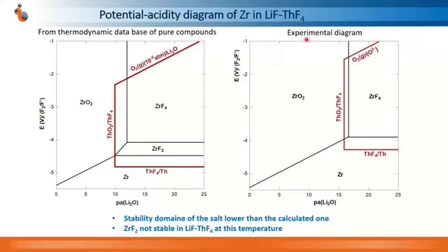Just a comment about lithium fluoride, thorium fluoride salt. We did some experimental studies of zirconium in this molten salt, and we have built the potential acidity diagrams of zirconium in lithium thorium fluoride salt, using only thermodynamic data of pure compounds, and we observed a stability domain of zirconium fluoride 2.